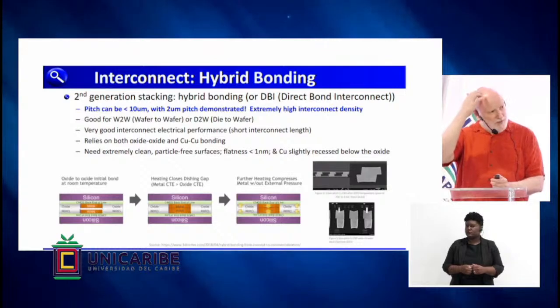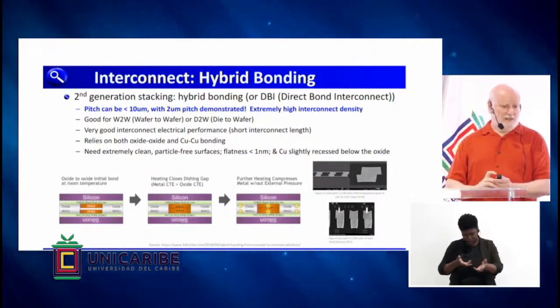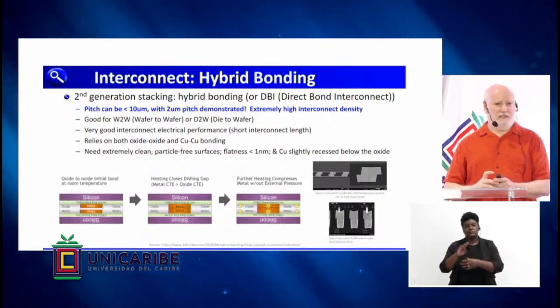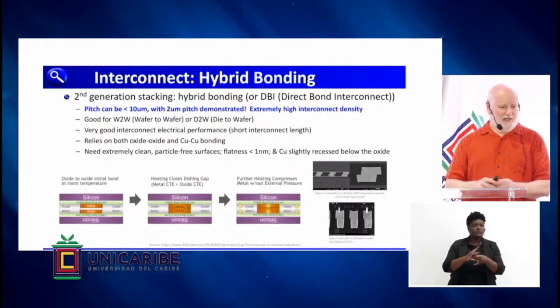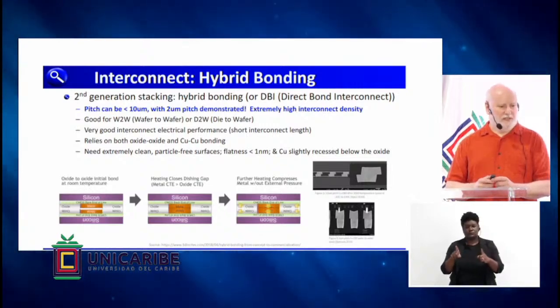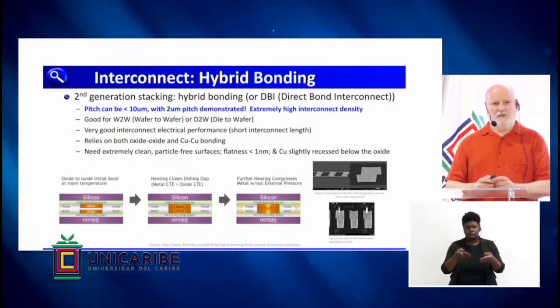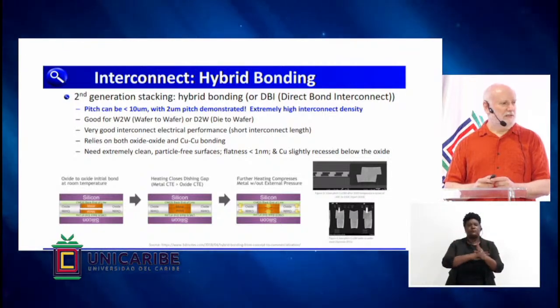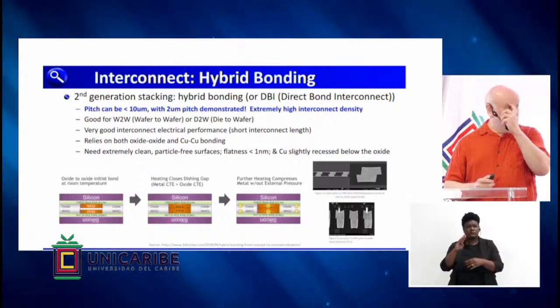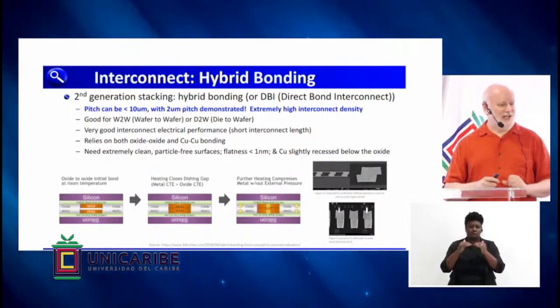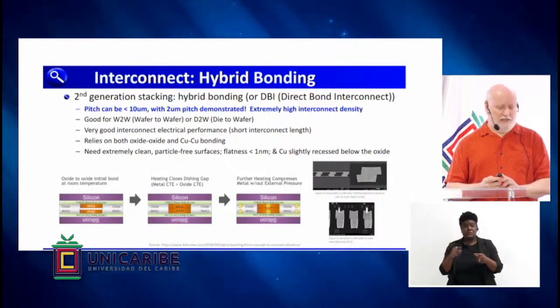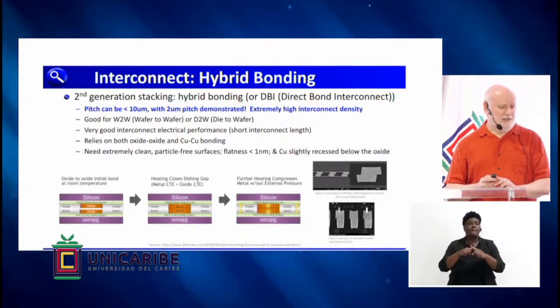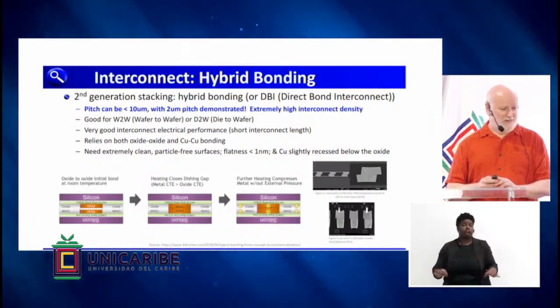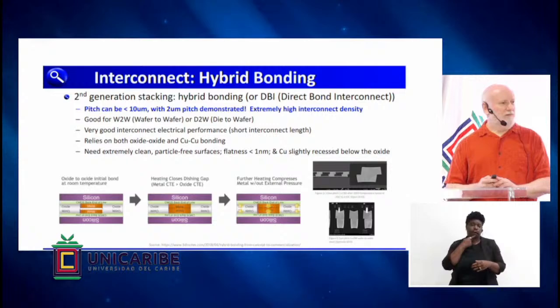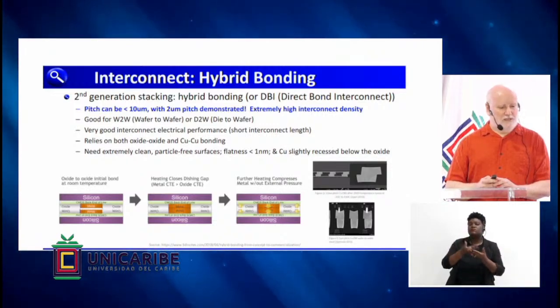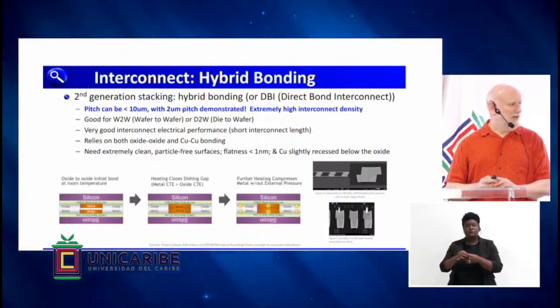So I'm going to talk about something called hybrid bonding. You might see it also referred to as DBI, or direct bond interconnect. This is kind of where the industry is going for very high performance. I mentioned before that you can do copper-to-copper bonding, diffusion bonding at an atomic level, but it was never really adopted by packaging. It wasn't adopted in the older times, but it's being adopted today. And it's going to be probably one of the most significant things in the packaging arena, in my estimation. So this is good for wafer-to-wafer bonding or chip-to-wafer bonding, sometimes called die-to-wafer bonding.